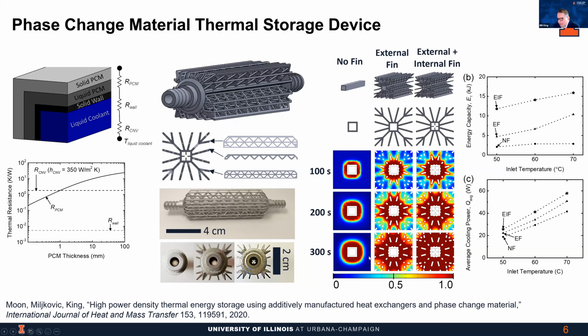So you can see finite element simulations of 3 devices. The first device is a device without any fins, so that's our baseline. And then by adding the fins outside the device, we get significantly more phase change. And then we also explored adding fins inside the device to reduce the thermal resistance to convective cooling inside the device. It turned out that was really meaningful. For the device that has both internal and external fins, we had 3 to 4 times improvement in energy capacity and about 2 times increase in the cooling power.